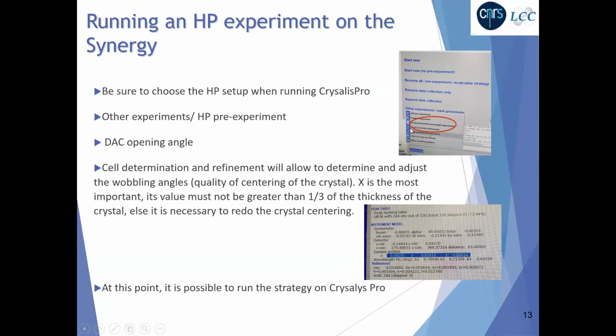Once the cell is determined, we have to refine it. And when we have refined it, we will be able to check the wobbling angle. So the X parameter is the most important. Its value must be not greater than a third of the thickness of the crystal. If it is not the case, it's necessary to redo the crystal centering, then redo the pre-experiment with the cell determination, refinement of the cell, and checking of the wobbling angle, the X parameter.